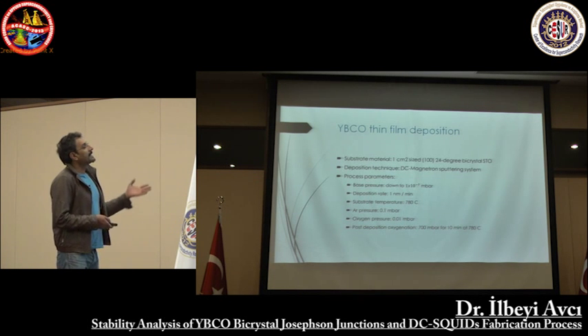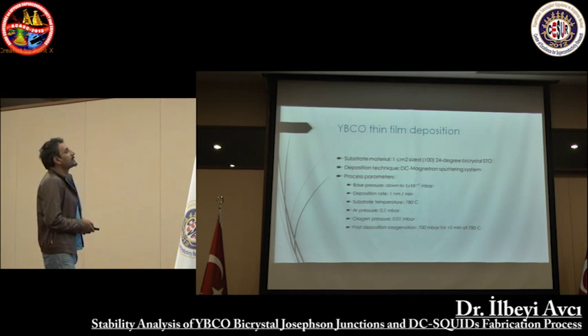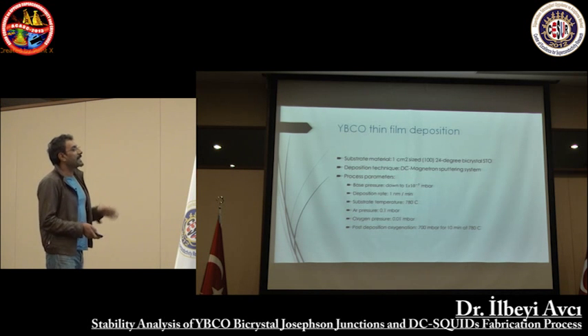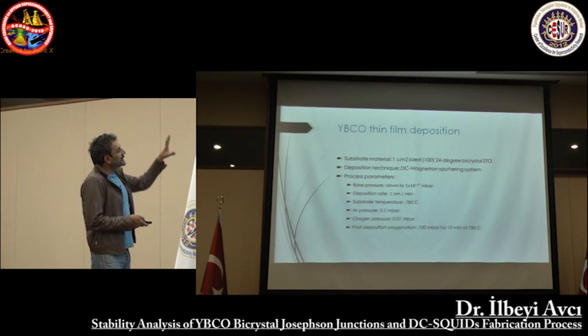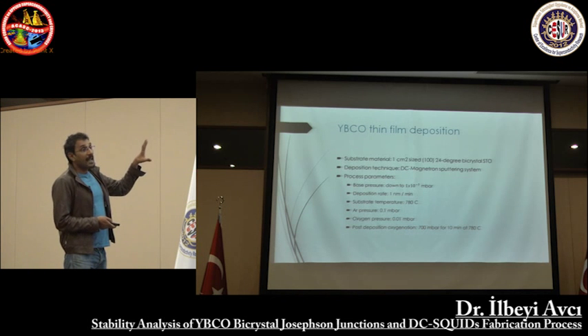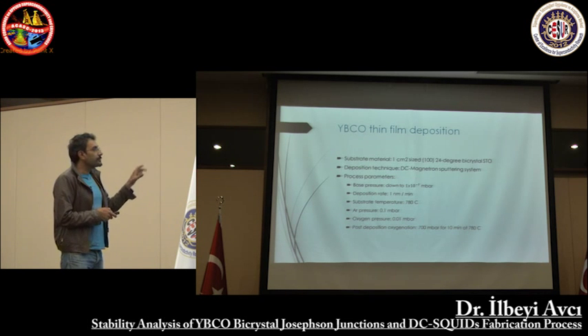and a 1 nanometer per minute deposition rate, and then some 780 degrees centigrade substrate temperature. Then there are the argon pressure, oxygen pressure, and the post-annealing. These are actually our standard, optimized parameters.